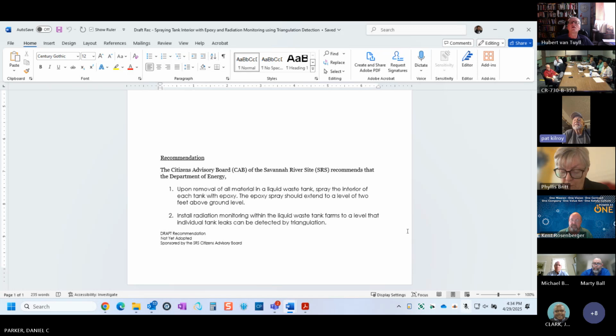Well, how thick is the steel in the base of these tanks? Half-inch? It varies by tank design. I think the thinnest one may be a half inch. Some of them are up to three-quarters to one inch. That's correct. And there's one other thing to say. As the carbon steel corrodes, it turns into rust, which is iron hydroxide. And iron hydroxide is a very good sorbent for multivalent cations and some anions. So it forms an additional barrier as it corrodes.